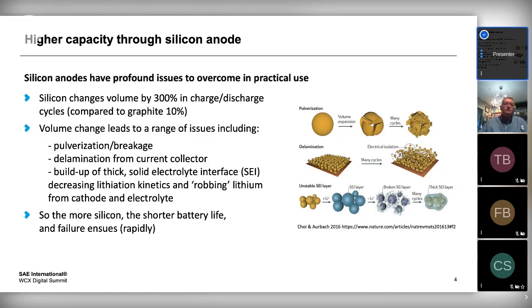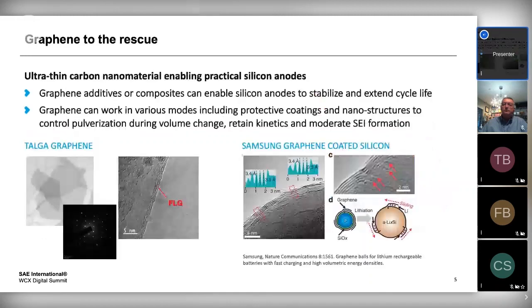These are profound problems if you want to get better performing anodes in the short term. But don't worry, we can fix it. Graphene can help solve this problem. It's been a problem for many years that has stumped many companies. And what we work on, amongst other things in our battery products, is that we've worked out that an ultra-thin coating of graphene, which can coat the silicon particles, can help to form a protective coating and different nanostructures that can control that pulverization as the silicon breaks down. It can help retain and stop the volume change from happening so harshly. It means you can set up the pathways for the lithium to intercalate into the particles without blowing them up, and you can decrease the amount of the solid electrolyte formation.